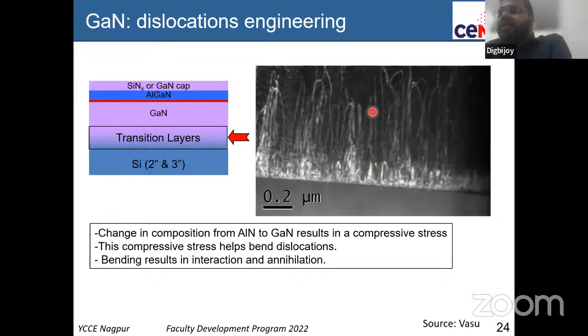Now, this reduction in the density of the white lines is not magical. There is a lot of material engineering that goes into these layers, managing the stress by using superlattices, grading, etc., which will enable you to reduce these defects as you propagate upwards. You cannot completely eliminate them, but you reduce them so that the device will see a fewer number of dislocations.